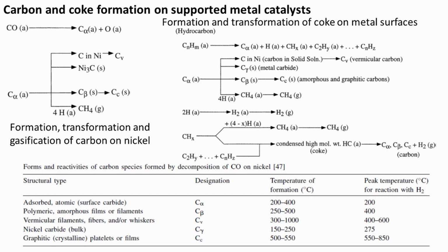Platinum, rhodium, and ruthenium catalysts, on the other hand, while equally or more active than nickel, cobalt, or iron in steam reforming, produce little or no carbon or coke. This is attributed to reduced mobility and solubility of carbon in the noble metals, thus retarding the nucleation processes.